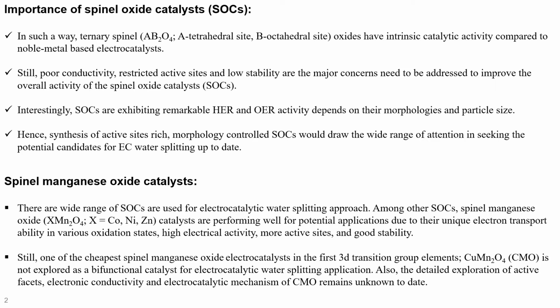In this way, spinel oxide catalysts, that is SOCs, are one of the most important and efficient electrocatalysts for electrocatalytic water splitting. Ternary spinel oxide catalysts have the AB2O4 structure, where A stands for the tetrahedral site and B stands for the octahedral site. Those have intrinsic catalytic activity compared to other noble metal based electrocatalysts. Still, the poor conductivity and restricted active sites are the major concerns we need to address to use these SOCs as efficient electrocatalysts for water splitting. Interestingly, SOCs exhibit remarkable HER and OER activity depending on their morphology and particle size. So, the synthesis of active site rich, morphology controlled SOCs would draw a wide range of attention to produce new electrocatalysts for water splitting.